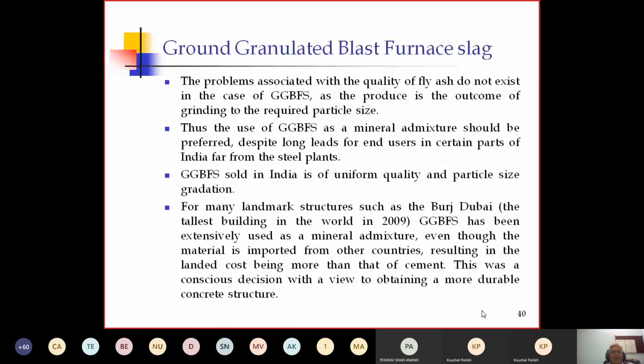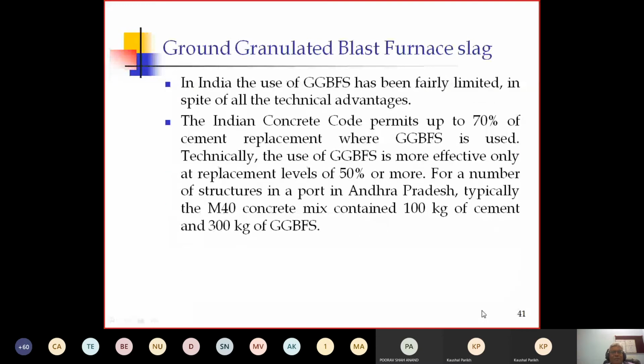In India, the use of GGBFS has been fairly limited in spite of all the technological advantages. The Indian Concrete Code permits up to 70% cement replacement where GGBFS is used. Technically, the use of GGBFS is more effective only at a replacement level of 50% or more. For a number of structures in a port in Andhra Pradesh, a typical M40 concrete mix contained 100 kg of cement with 300 kg of GGBFS. So in the typical range, 50% or more can be used as cement replacement with GGBS.